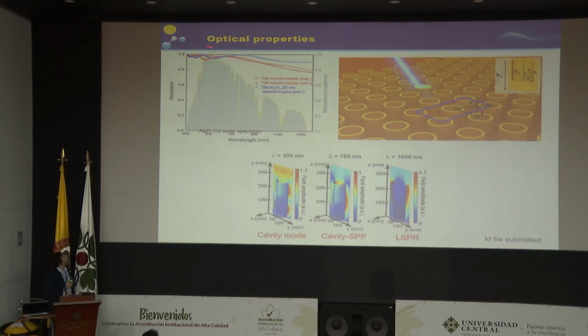And here is the absorption of our materials. You can see that they really provide exceptional absorption properties in the visible and near infrared. The experimental curve of pure titanium nitride is the solid red curve. We can absorb 95% of light at 470 nanometers, or 97% if you consider the range between 300 and 1100 nanometers. Of course, if you modify the structure with alumina, for example, we can modify the interaction with light, and we can reach 97% of light even if we extend the range up to 2200 nanometers.